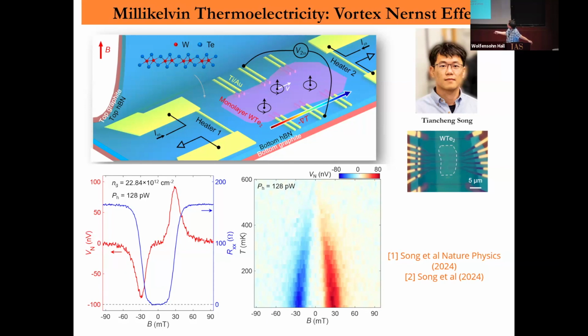Then you have a peak here, which signifies that now you have a mobile vortex. You apply a temperature gradient, this vortex moves, so it has a Nernst voltage signal, and then it comes back to zero, because after that you no longer have the vortex—you go to the normal state, with normal electrons that don't have a superconducting condensate.